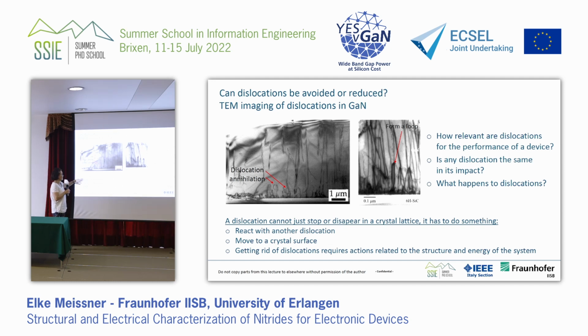And what you now have to see is that the dislocation cannot just stop in the layer or disappear because it stores energy. So it cannot just disappear in a crystal. It's built up in a crystal as a displacement energy, so you cannot just put it back to the place. This will not happen, so it has to do something. So if you want to get rid of dislocations, you have to do some action.